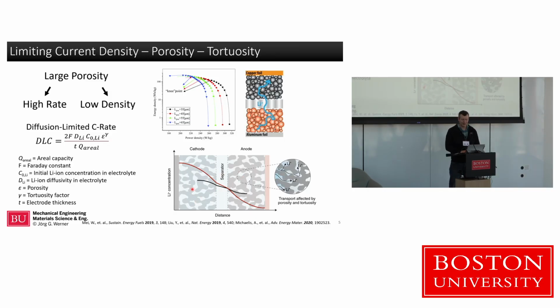Because even though our distance or thickness of the battery is 100 micrometers, the lithium ions might have to travel 300 micrometers in real path. And if you've ever walked around Boston or driven around Boston, that's exactly what you have. I want to get over there, but I have to go around 10 miles to avoid all the one-way streets, right? That's essentially your tortuosity. So these are handles we can deal with. Porosity, we don't want to increase too much because then we lose energy. Tortuosity, on the other hand, is just how do we architect that porosity.